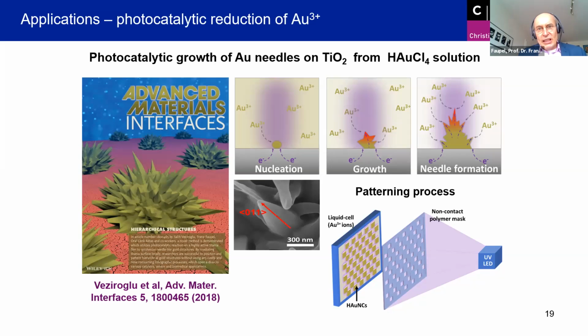We use photocatalysis not only for cleaning and other applications, we also use photocatalysis for photocatalytic deposition. So here we start with a metallic solution. For instance, in case of gold, we use chloroauric acid solution, and then we photocatalytically reduce gold atoms from the solution, and we form metallic nanostructures on the surface.